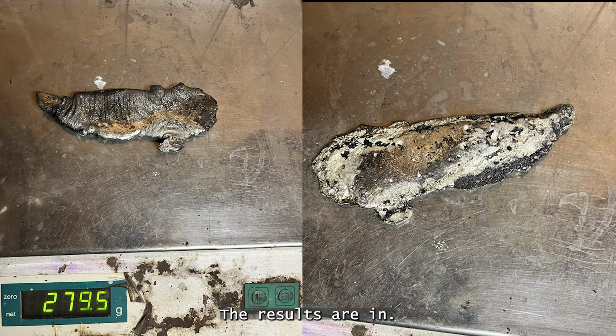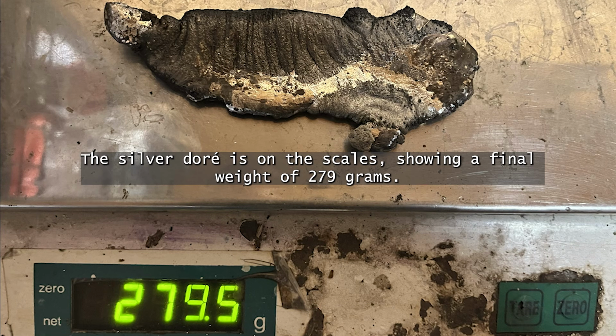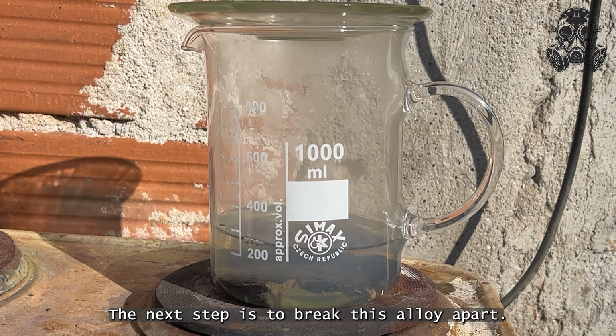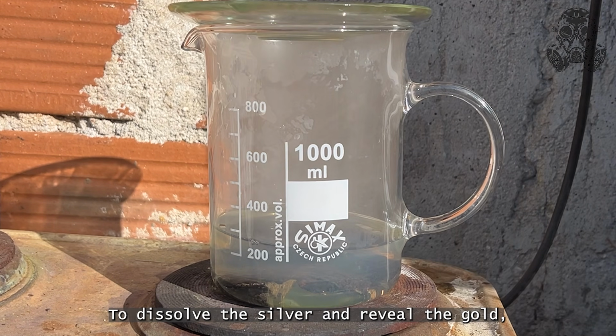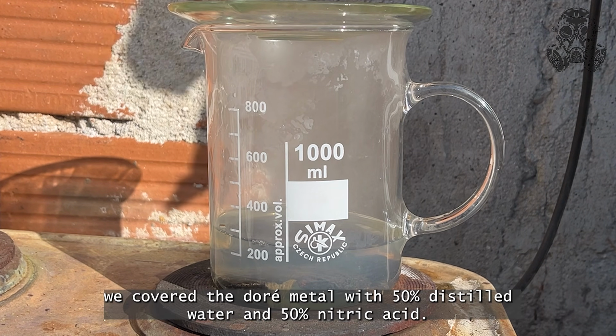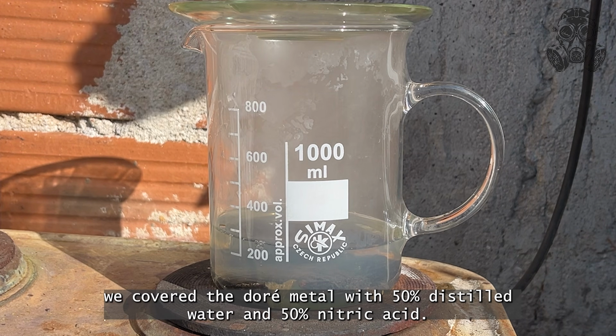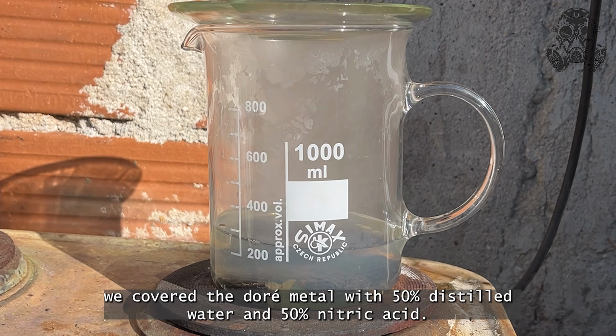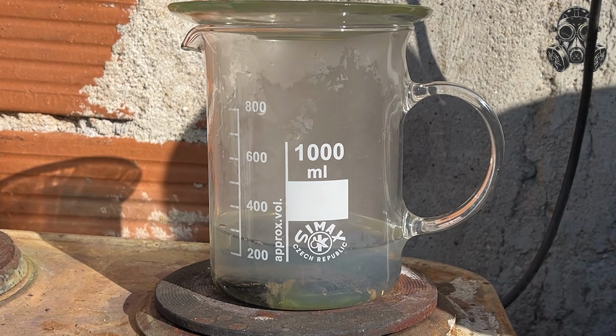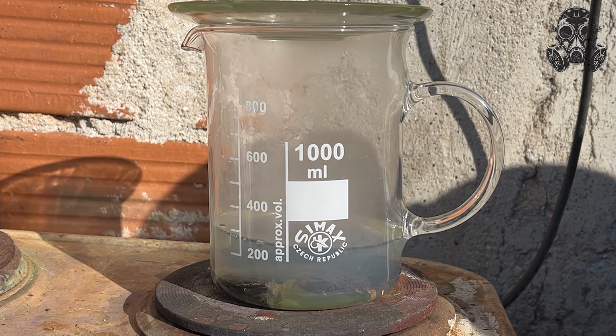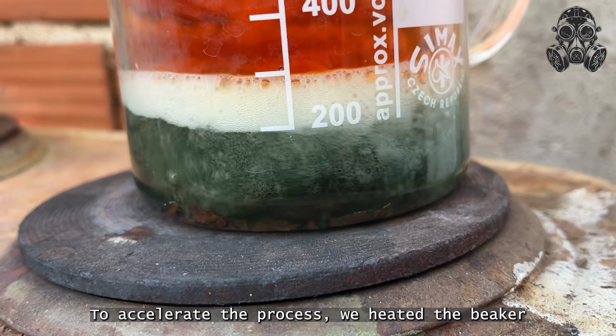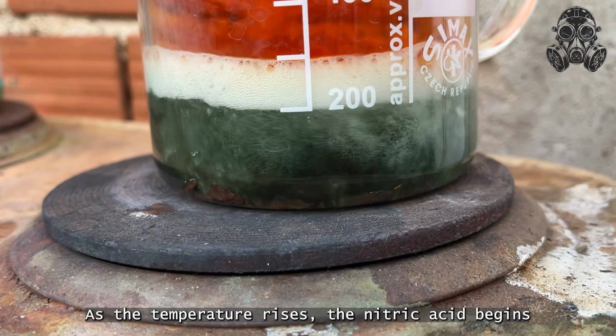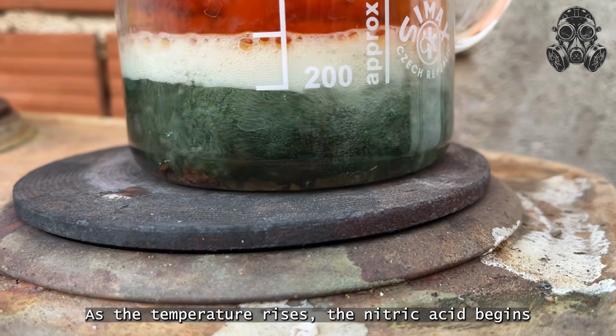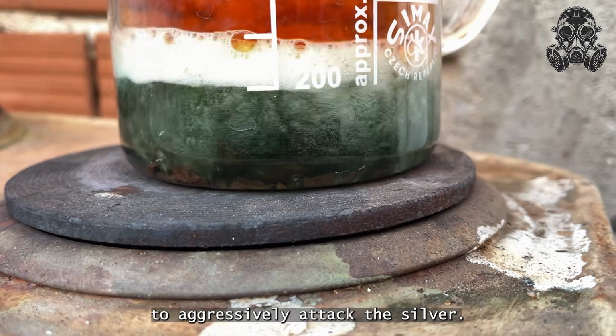The results are in. The silver doré is on the scales, showing a final weight of 279 grams. The next step is to break this alloy apart. To dissolve the silver and reveal the gold, we covered the doré metal with 50% distilled water and 50% nitric acid. To accelerate the process, we heated the beaker. As the temperature rises, the nitric acid begins to aggressively attack the silver.